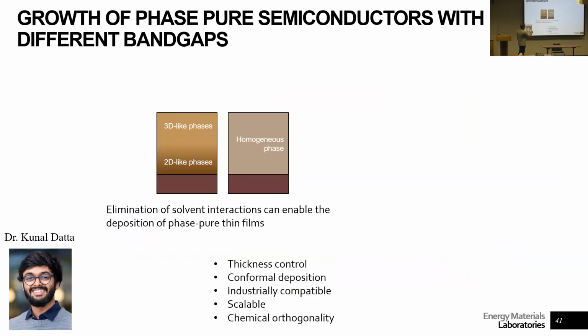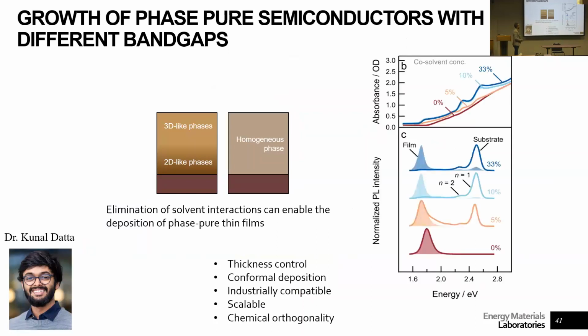And then the other thing is that we want homogeneous phases, right? So we don't want to have one phase on one side and another phase on another. So a lot of what my group is doing is trying to make phase pure films, basically like this guy here, the emission only in one band, to have a good semiconductor. These here, you can see several emission peaks. Those are going to be detrimental to a device, because we have many different phases kind of forming around.